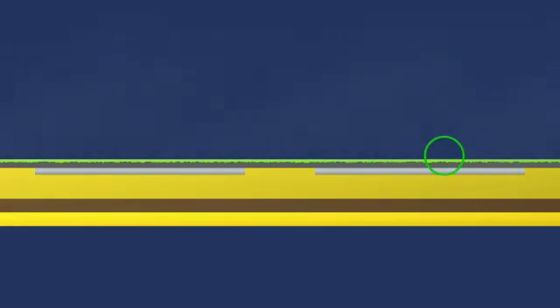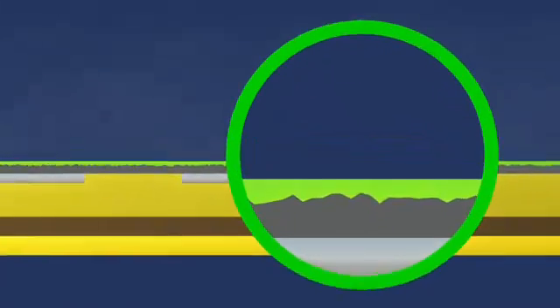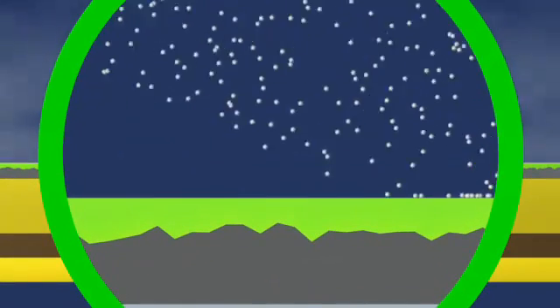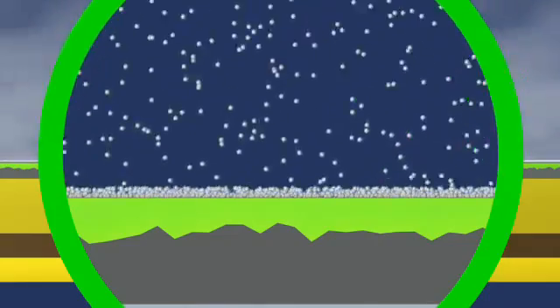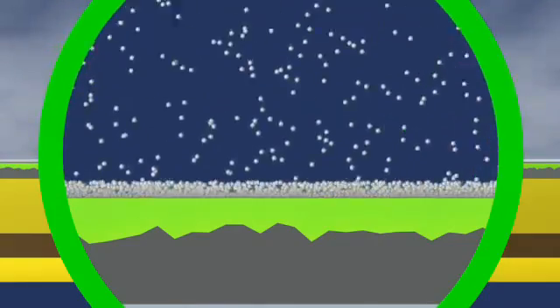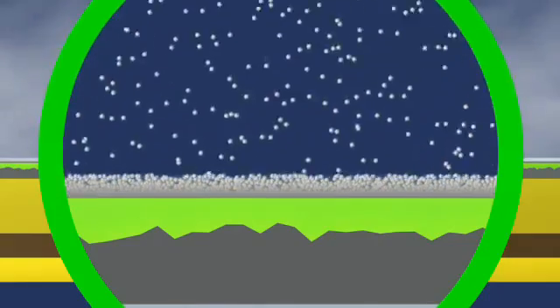The surface is roughened by wet chemical etching. A passivation layer is then deposited. It protects the surface from environmental impurities. This is followed by further metallization and structuring, with coating, exposure, development, and etching.